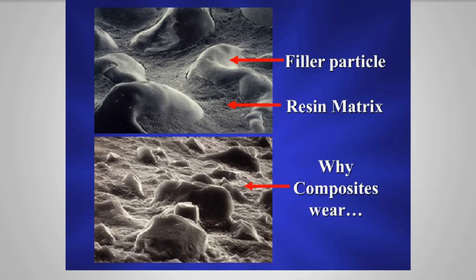Smaller particle composites and nanofilled type composites tend to wear less than larger particle composites simply because they present a smoother external surface and they're less prone to this plucking phenomena, and if a particle is lost, the hole left behind is that much smaller.